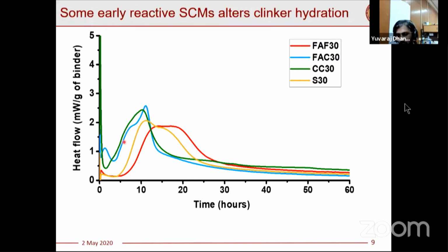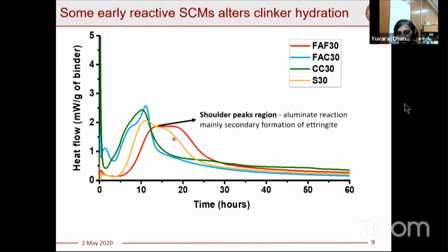However, when you start looking at the profiles of calcined clay and the class C fly ash, you see profiles more like a truncated core. So typically, to read these hydration curves, what you see is a kind of shoulder peak, a very small one here, but in the case of class C fly ash, you can see a dominant shoulder peak. This corresponds to the reaction of the aluminates. So basically, you have the main hydration curve from the C3S reaction, and then you have the aluminate reaction, which corresponds to the secondary formation of ettringite.